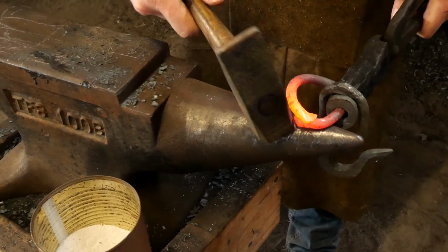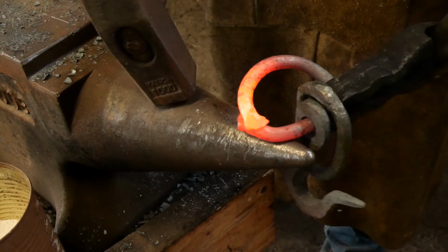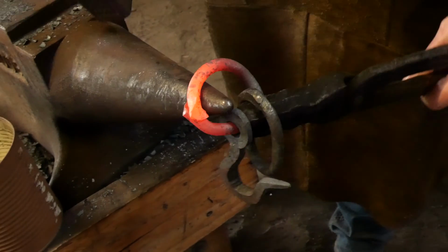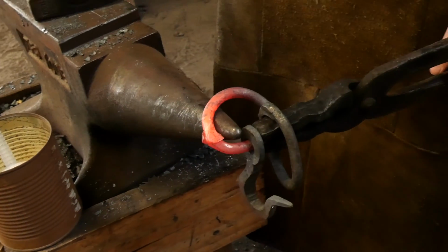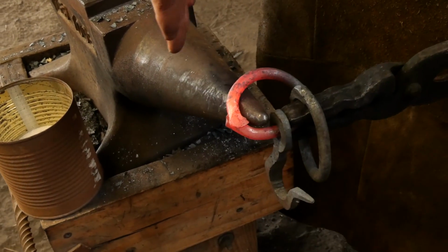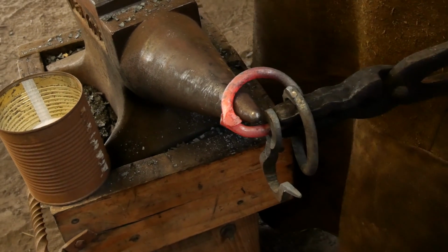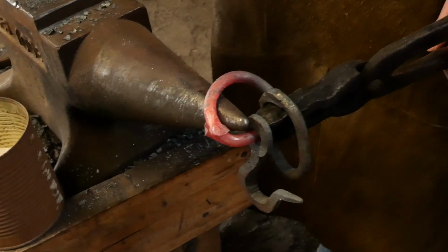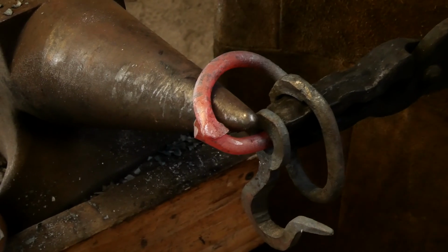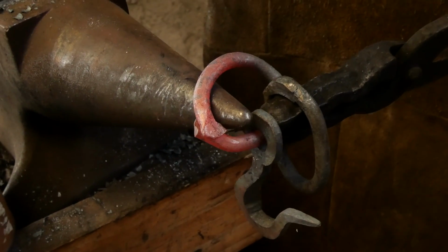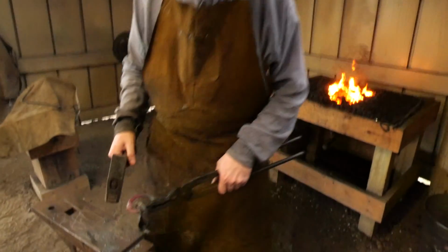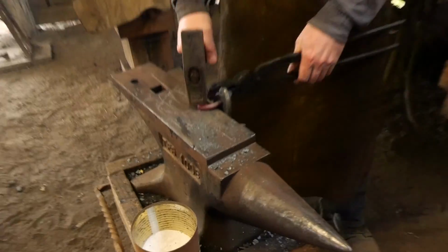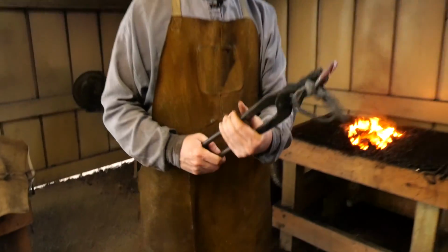You can see I've got a little bit sticking out here over the edge. I want to, if I can, try and knock that back in. Anything that we've got hanging out over the edge, there's nothing for that to forge weld to. And we want all of this end piece here to really weld up nicely. So we've got this ready to go in for the forge weld, but we've got some stuff hanging off of it, which is going to make this a little bit trickier.